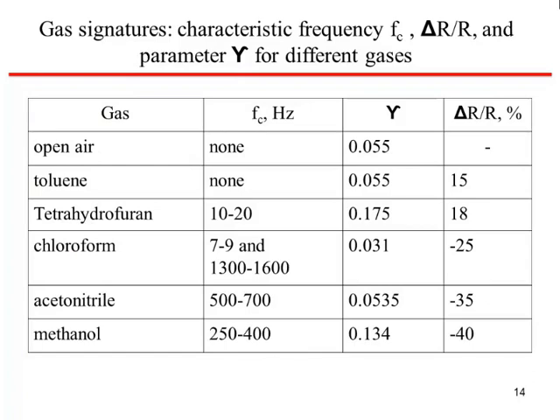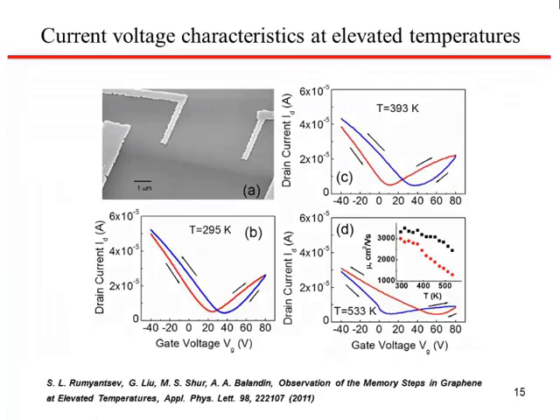In fact, you don't even really need the entire delta-R over R. Professor Shur feels that just the sign — positive or negative — which emerges very early without having to wait 500 seconds, combined with the noise parameters, can be used to distinguish between the gases.